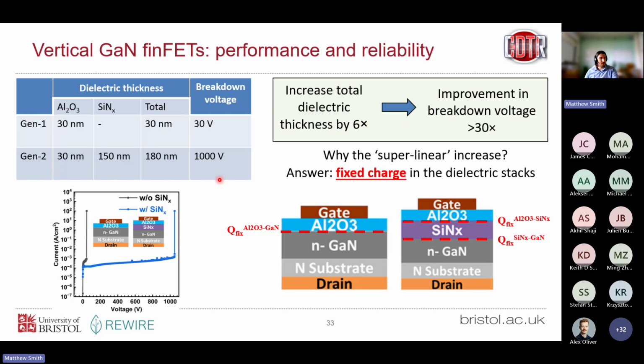So one thing we did look at was, why do we see such a big increase in breakdown voltage when all we've done is increase the thickness of our dielectric by about 6 times, and we see somewhere between a 30 and 35 times increase in breakdown voltage? You would expect a linear scaling if it was just a case of the dielectric layer redistributing the electric field. So what we found was the fixed charge distribution in these layers is very important, which wasn't previously reported.